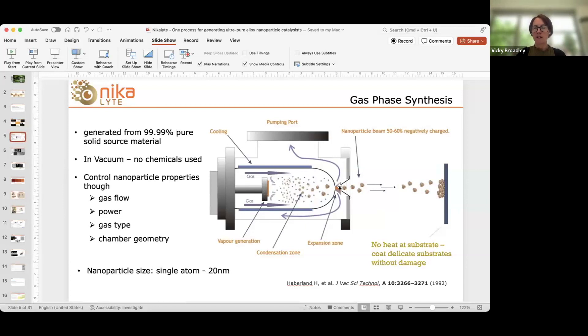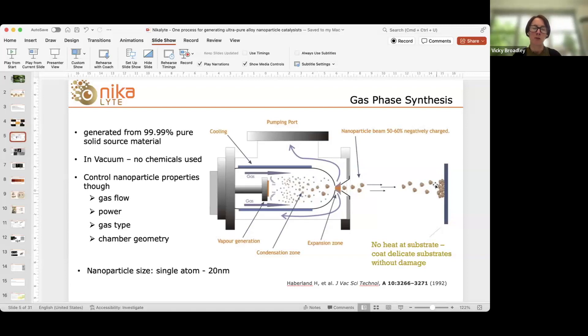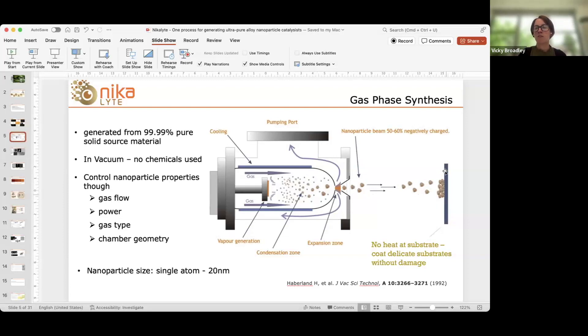As these atoms move through the aggregation zone or nanoparticle generation zone, they come into contact with other atoms and ions, lose energy, and start to coalesce or condense. This is the condensation zone where nanoparticles are formed — where we move from individual atoms to clusters of atoms. The properties of these clusters as they grow and travel through this region depend on the parameters of the zone, which we can control externally by changing gas pressure, power on the magnetron, the type of gas, and the distance between the target and the exit aperture.